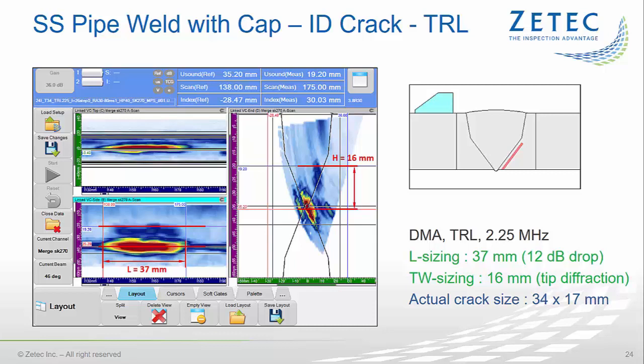On the contrary, when using DMA probes in stainless steel welds, it was empirically demonstrated that the 6 dB drop technique has a strong tendency for undersizing the length of the flaw. The 12 dB drop, or even the full amplitude drop, provide more accurate results. Full amplitude drop means that we follow the response of the flaw down to the acoustic noise level.